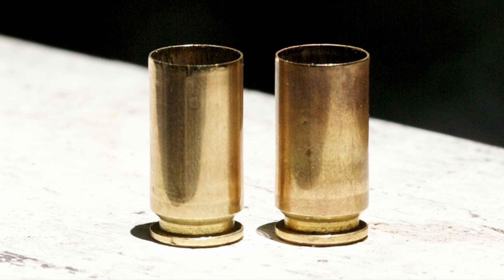The annealed brass made it a minimum of 35 cycles and one piece even held on for an impressive 48 cycles.